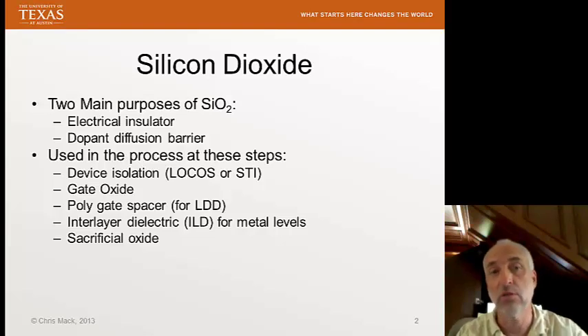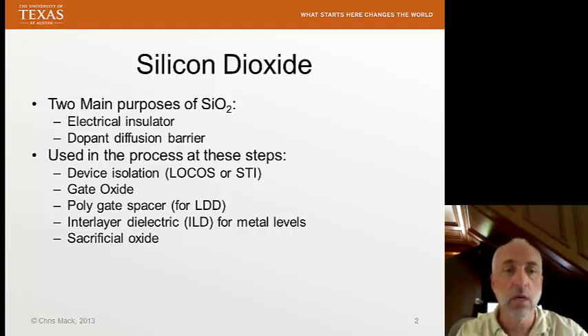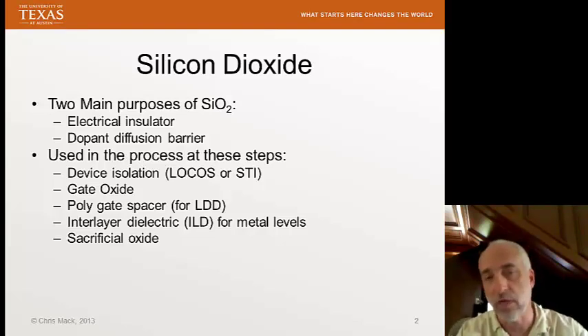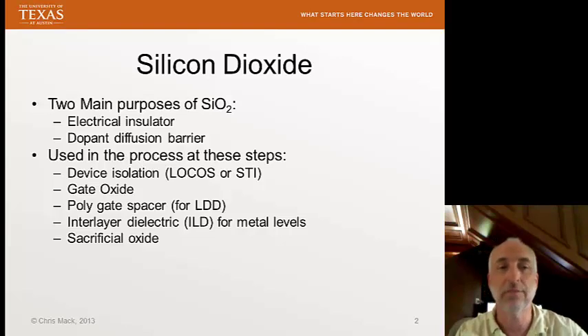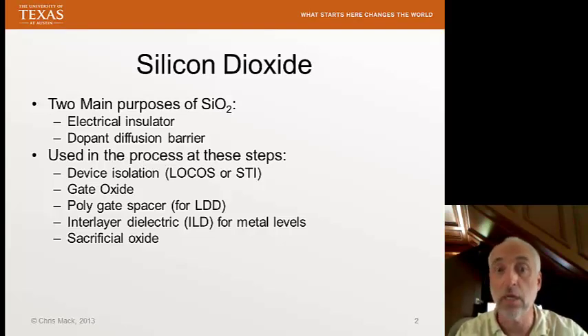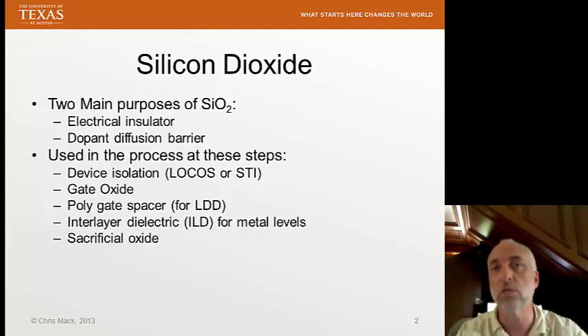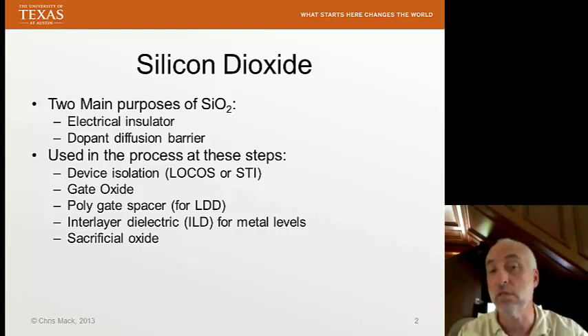We use oxides for the gate oxide. In the MOS transistor, the O is an oxide, and silicon dioxide forms a very good gate insulator. We use it for the polysilicon gate spacer — we put a spacer on the outside of the polysilicon gates for the lightly doped drain process. The interlayer dielectric isolates metal levels and metal lines in a single level; it's basically the insulator surrounding the copper lines wiring up our transistors. And there are several places where we use an oxide as a sacrificial layer for implanting through or as part of the process that will eventually get stripped off.